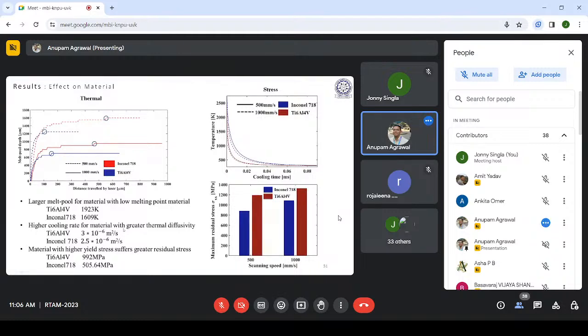A higher cooling rate has been obtained for material with greater thermal diffusivity. The thermal diffusivity of Inconel is low. The thermal diffusivity of titanium is high. So higher cooling rate for higher thermal diffusivity. We can see from this here. And also the material with higher yield stress suffers greater residual stress. Ti6Al4V has much higher yield stress, and also it has very high residual stresses built up in the part. So with choice of material also some recommendation can be given.